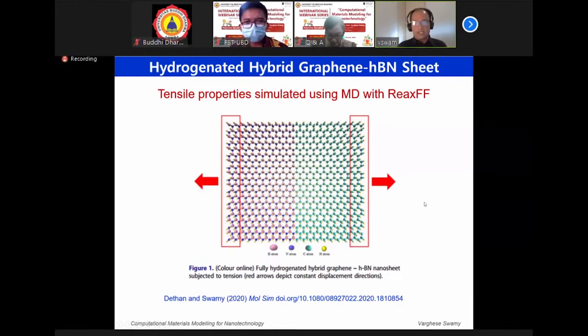So you create this in your computer, and then you clamp these two sides, or select those two sides, and apply velocities in opposite directions, and you are pulling it apart. You can analyze the results after the molecular dynamics runs and see what happens to the material, especially its elastic properties, and after the elastic regime, how it might behave either in a ductile fashion or a brittle manner.